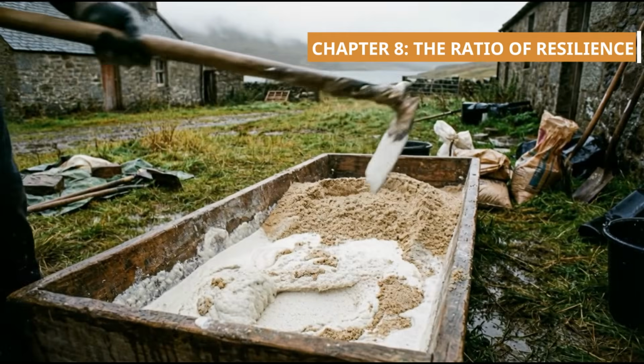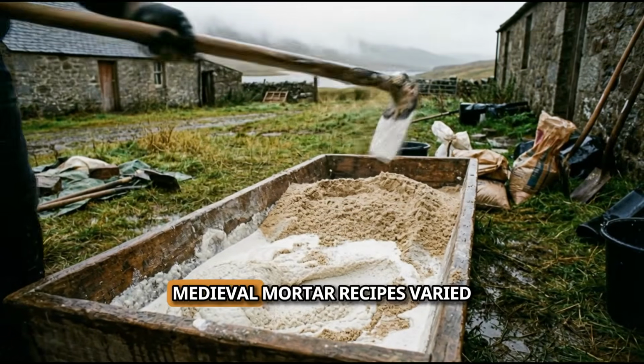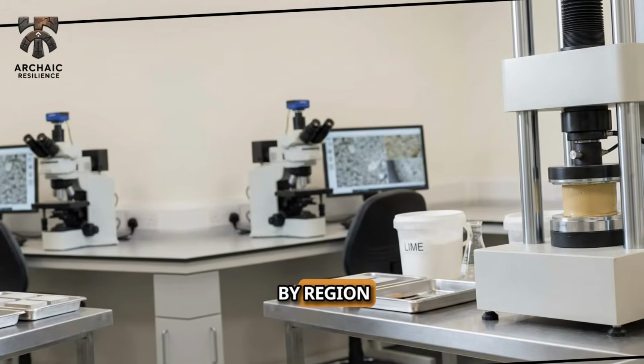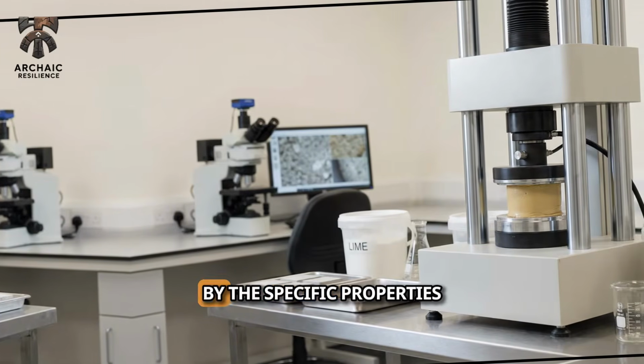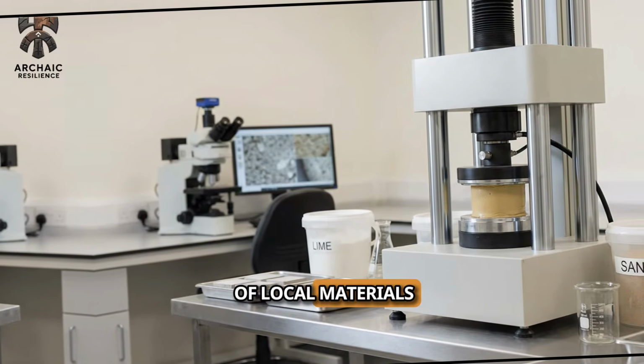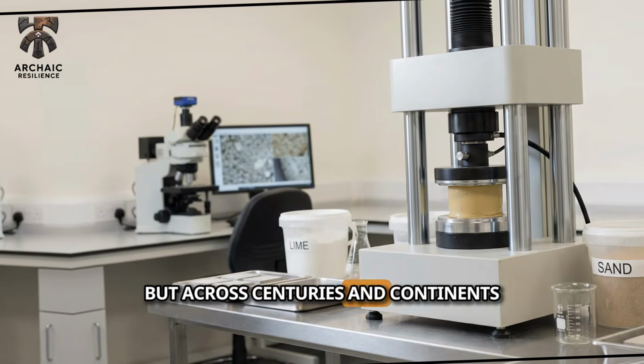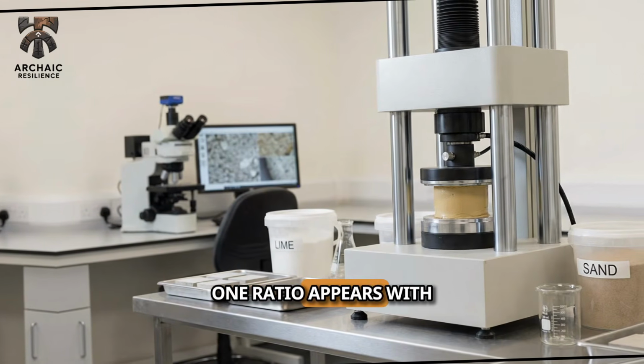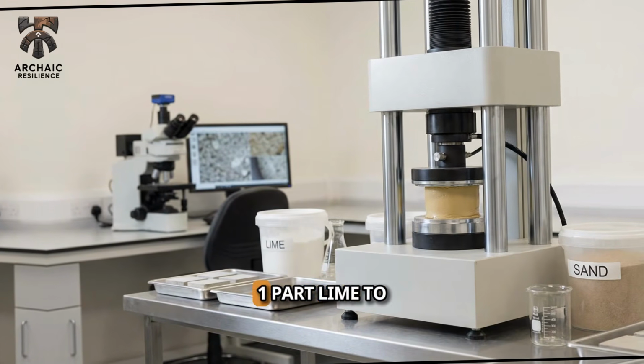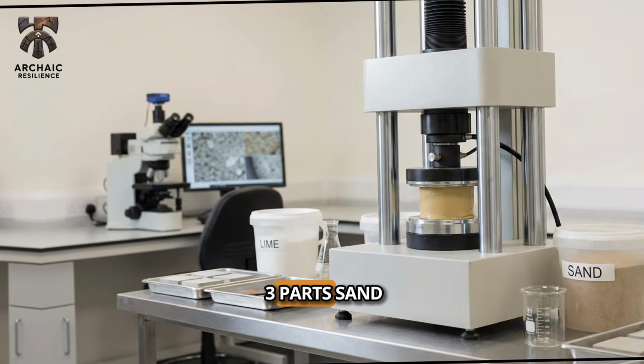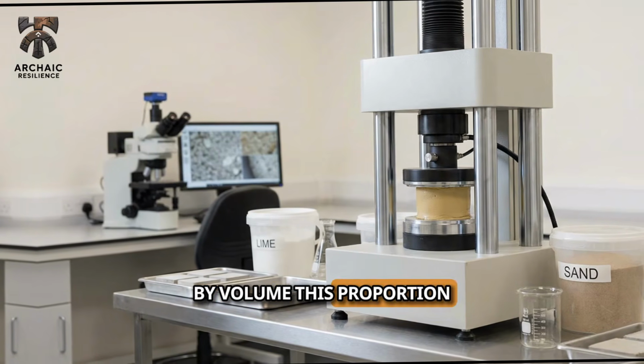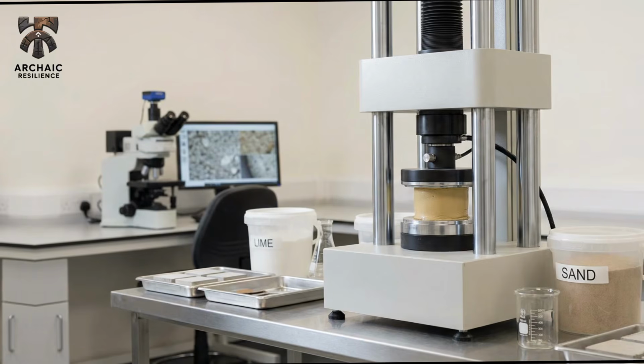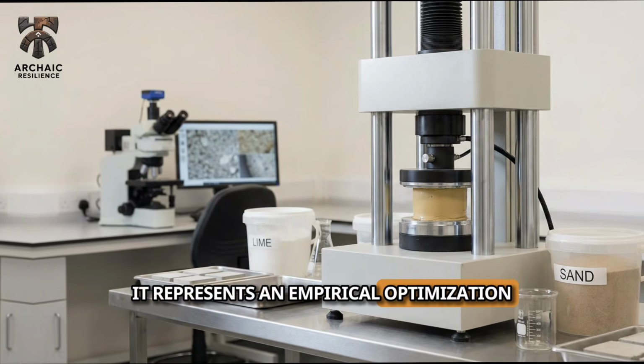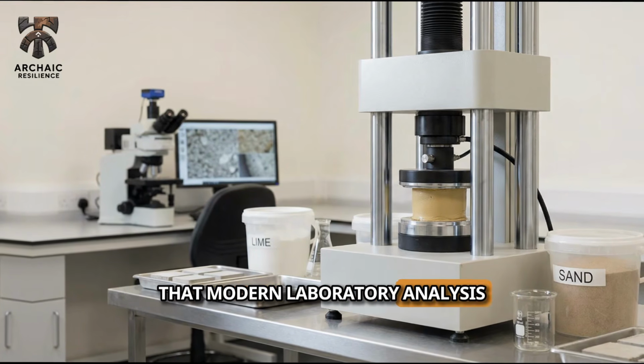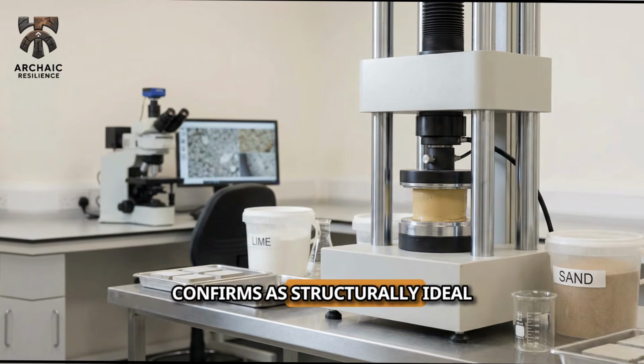Chapter 8. The Ratio of Resilience. Medieval mortar recipes varied by region, by application, by the specific properties of local materials. But across centuries and continents, one ratio appears with remarkable consistency. 1 part lime to 3 parts sand by volume. This proportion is not arbitrary. It represents an empirical optimization that modern laboratory analysis confirms as structurally ideal.